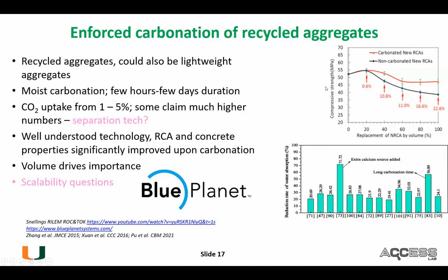But the advantage of this, even though the uptake is very low, is that recycled concrete aggregates don't have the best properties. They absorb a lot of water, they're weak in strength, etc. By carbonating them, a lot of data has shown that you improve the properties, you improve the strength of the concrete, you increase the water tightness of the concrete, etc. And it's important because 80% of your concrete is still the aggregates, so if 80% of it has 1% uptake, that's still a pretty decent number.